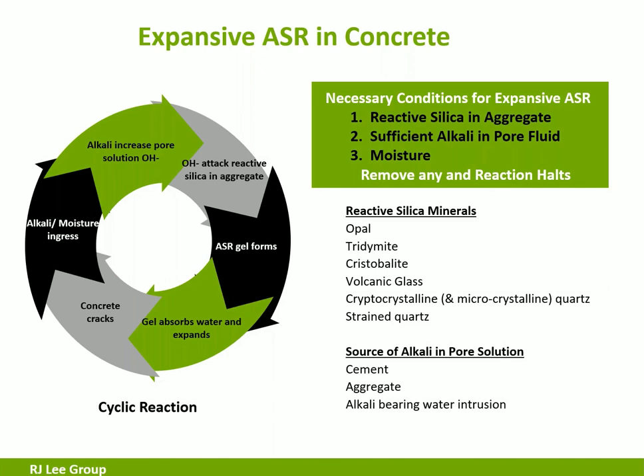So how does it work? Basically, you have a reactive silica component in your aggregate. Some of those reactive components are opal, tridymite, and volcanic glass. So basically, it's a type of quartz that is not ordered. And you'll also need sufficient alkali in the pore fluid, and moisture.